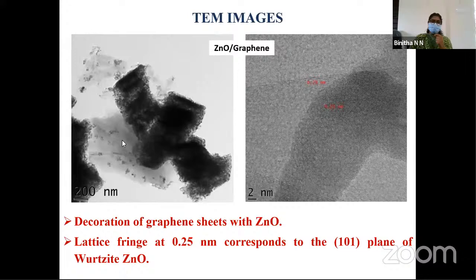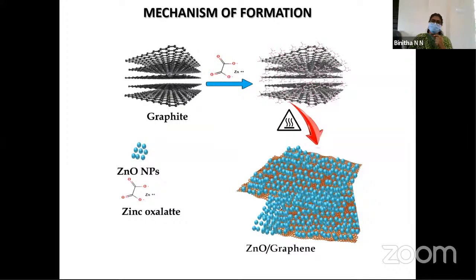These are the TEM images of the graphene zinc oxide nanocomposite. The bunches of zinc oxide spherical particles are dispersed over graphene sheets. And the lattice fringes corresponding to zinc oxide are also visible in the high resolution TEM images. About the mechanism of formation. Initially, graphite is ball milled with zinc oxalate. Zinc oxalate species is incorporated between the layers, and after thermal treatment, it is converted into spherical zinc oxide bunches decorated on graphene nanosheets. It is evident from the TEM photographs.